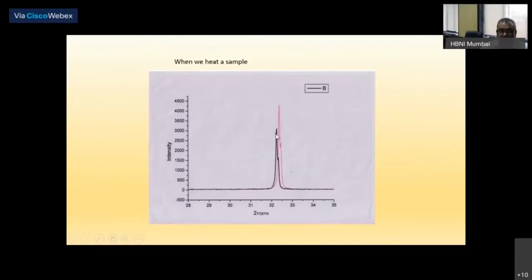This is the Debye-Waller effect. The sharpness did not change, but the intensity changed. So the intensity became less. And of course, another important factor whenever we're designing a scattering experiment is the Q resolution. Here with X-rays, the Q resolution allows me to see the difference between the K alpha and K beta lines of copper.